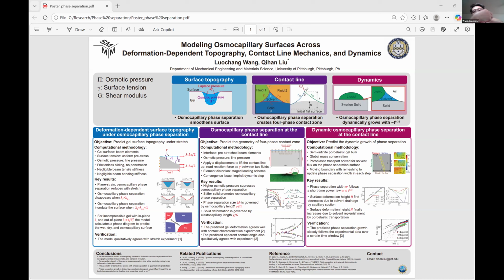When a droplet sits on a swollen gel, the solvent can exude near the contact line and form a phase separation, which creates a four-phase contact zone. The objective for this part is to predict the geometry of that zone. We use a similar finite element setup, only modeling the surface as well. And this time we lift the contact point up. And the equilibrium state is how the contact zone looks.